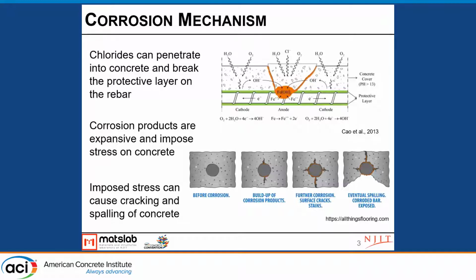Chlorides can penetrate into concrete and break the passive layer on the rebar and initiate the corrosion. The corrosion products are expansive and they can impose stress on concrete. This stress can cause cracking, and the cracks can propagate and also ease the penetration of chlorides into the concrete and cause more corrosion. And finally, these cracks can cause spalling of concrete and expose the rebar.